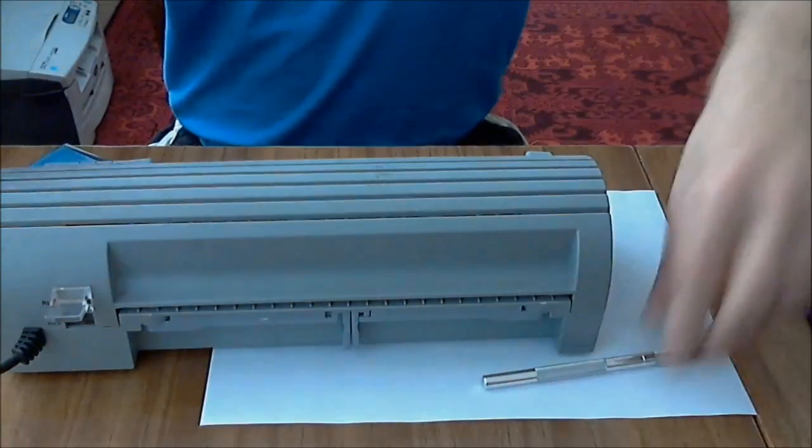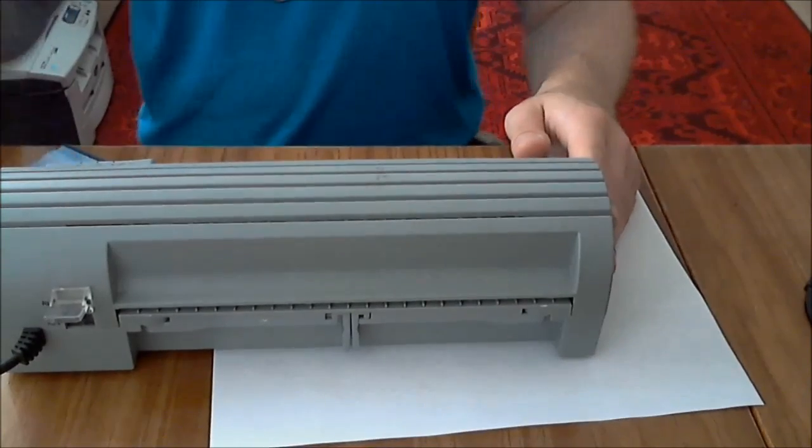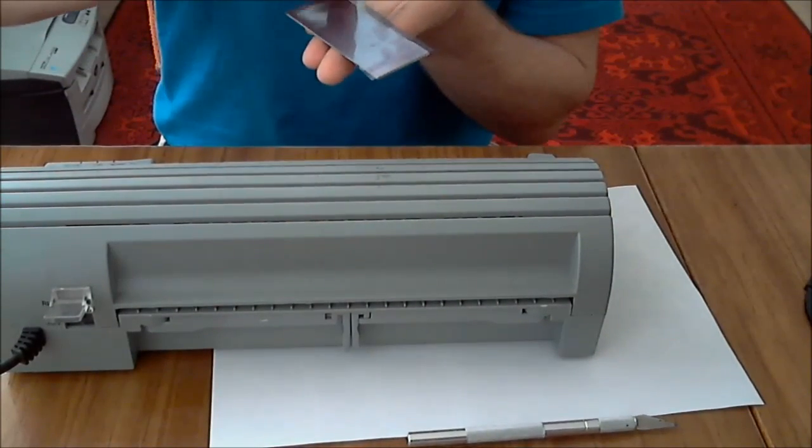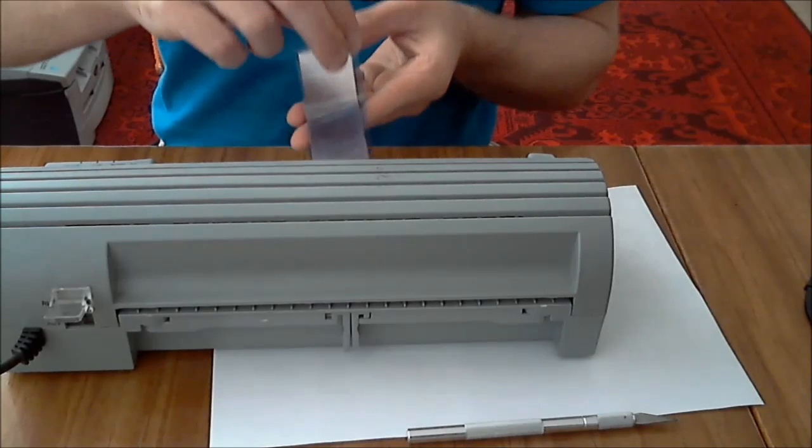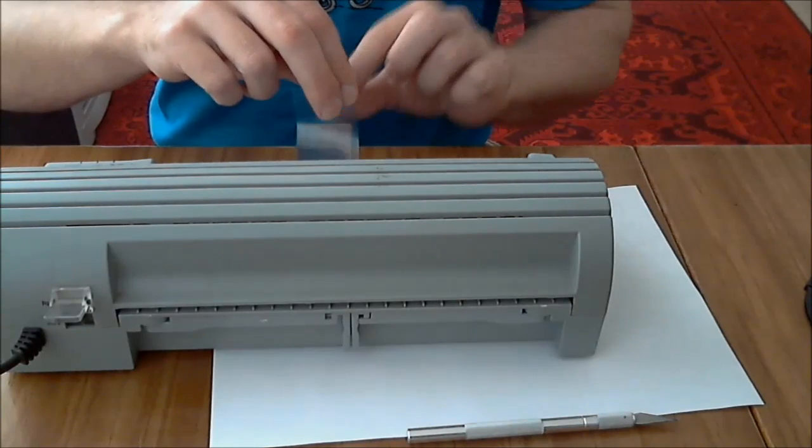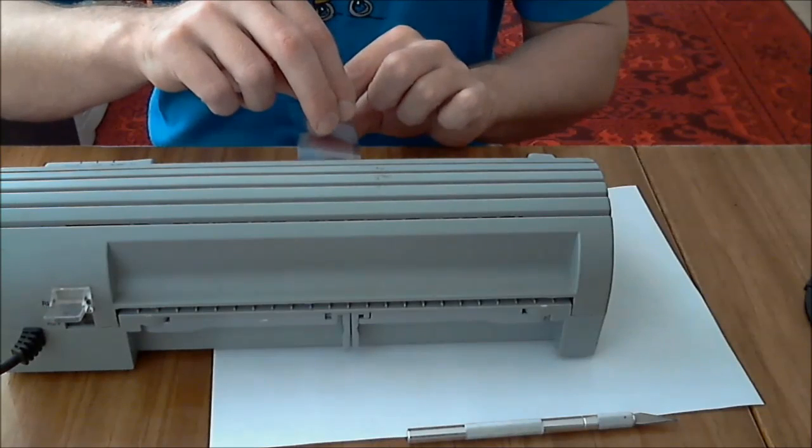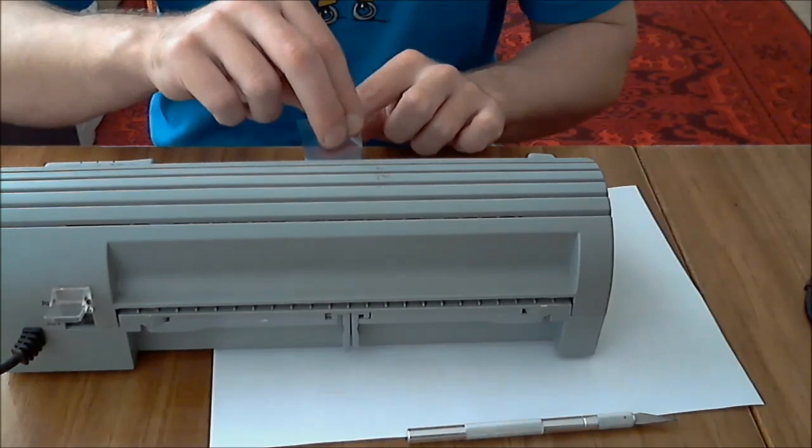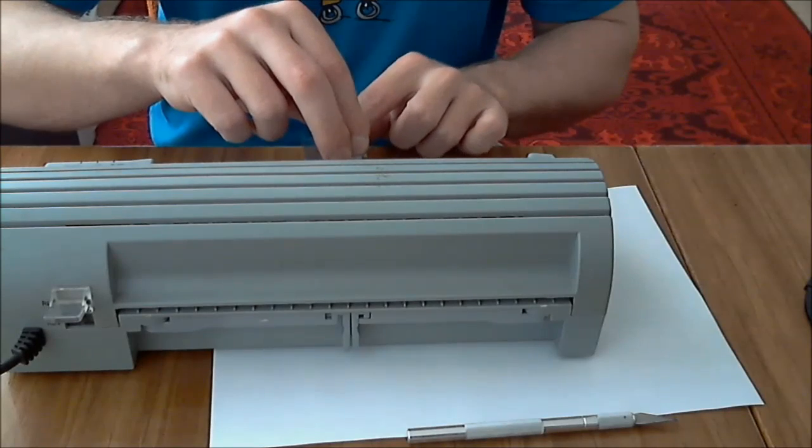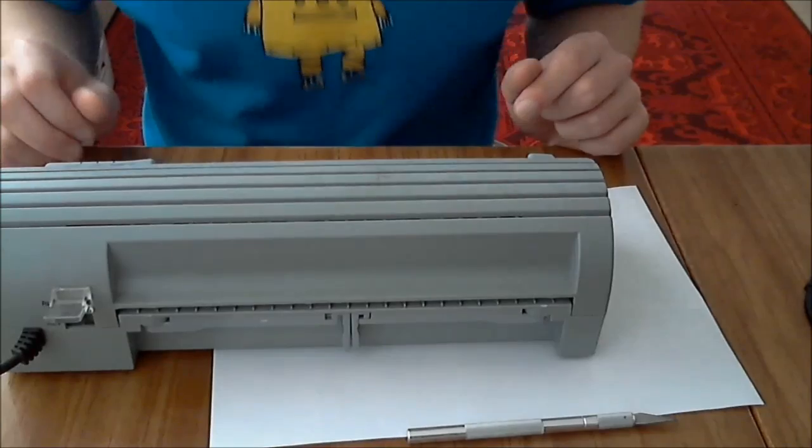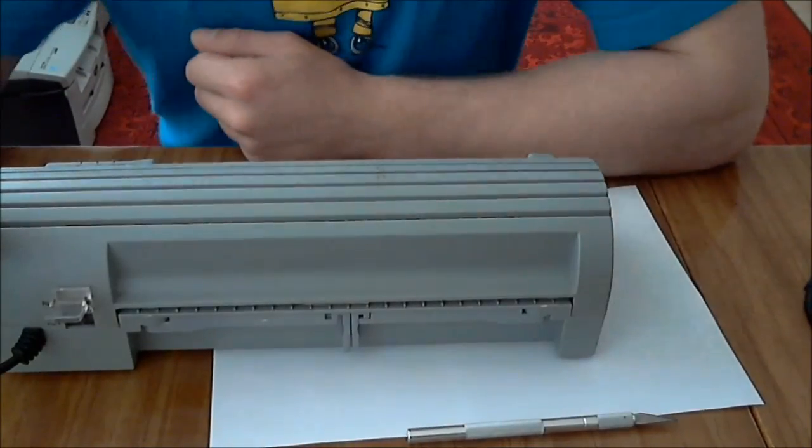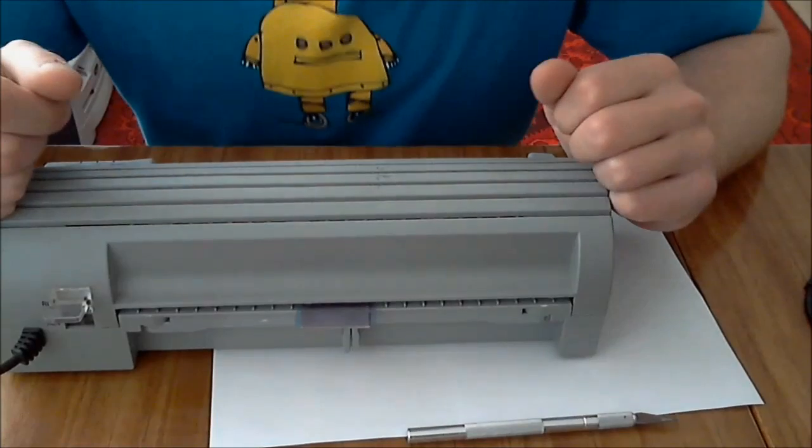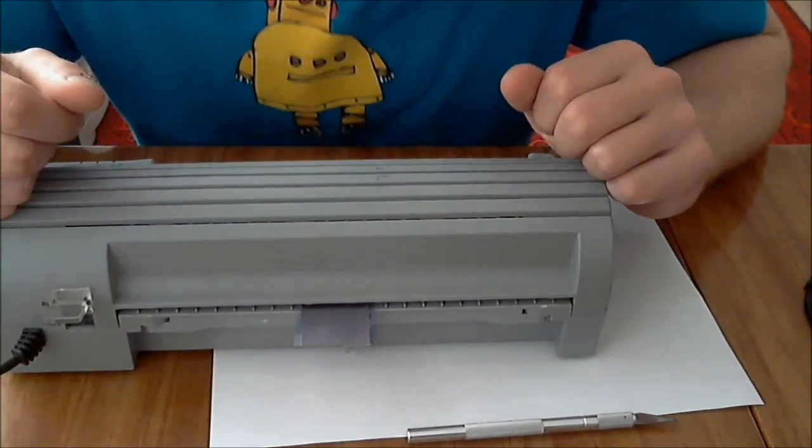And you get your laminator. Just turn it on. Try to peel it out of the side of the PCB and start running it through, just a couple times to get it to stick. Just remember, don't do it with your laminator completely warmed up because photoresist is also temperature sensitive so it can harden while you're running it through the hot plates of the laminator.